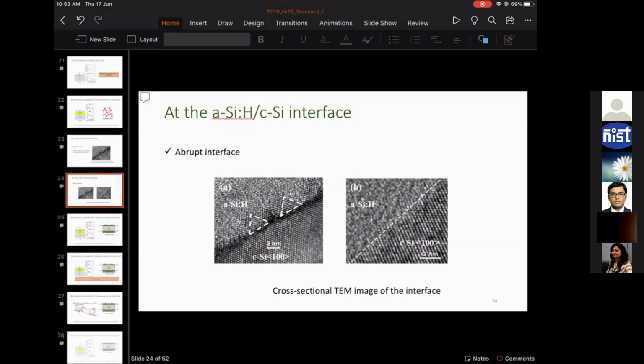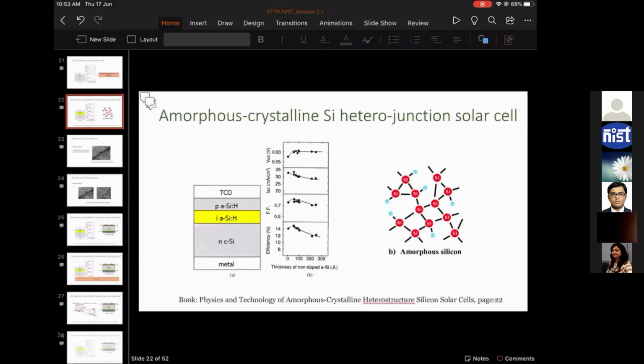Yeah, I got your question. So your question is leaning more towards the amorphous silicon thin film solar cell. Why I am saying this? Because in an amorphous silicon thin film solar cell, it is the intrinsic amorphous silicon absorber layer that you use in place of crystalline silicon. So what happens if you expose an amorphous silicon thin film solar cell to sunlight? There is a degradation that happens with time inside your amorphous silicon that is called the Staebler-Wronski effect. It is associated with the mobility of the hydrogen bond across your amorphous silicon.